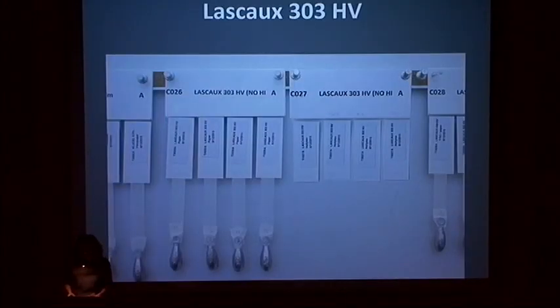The Lascaux 303 on paper remains adhered to the flat hinge, but the Lascaux 303 on Hollytex have all failed. We repeated this test 3 times to confirm the findings, and always we had the same result. This underscores the importance of the bonding system and the carrier of the hinge, which plays definitely a critical role.